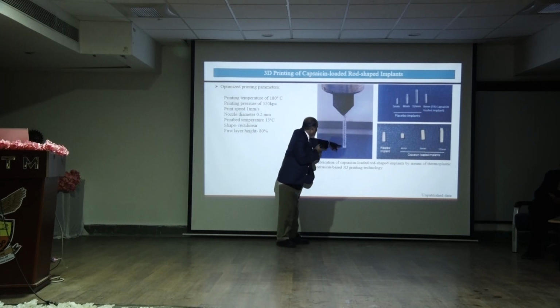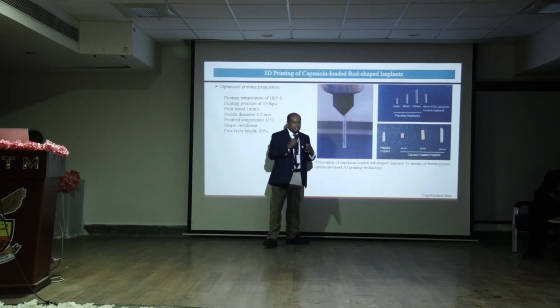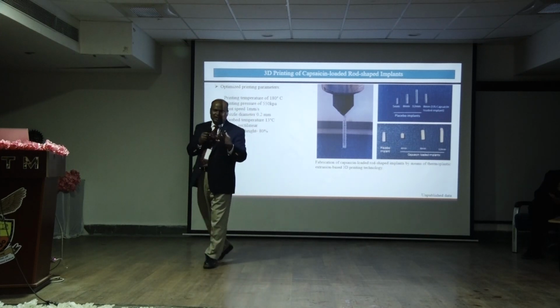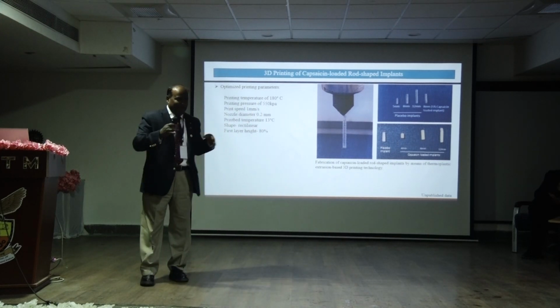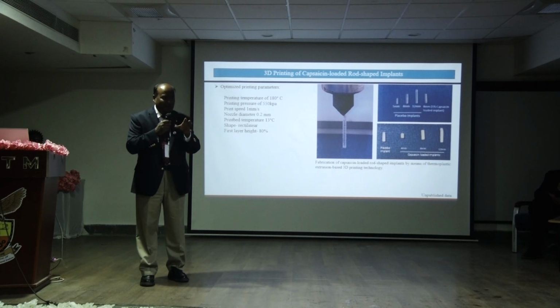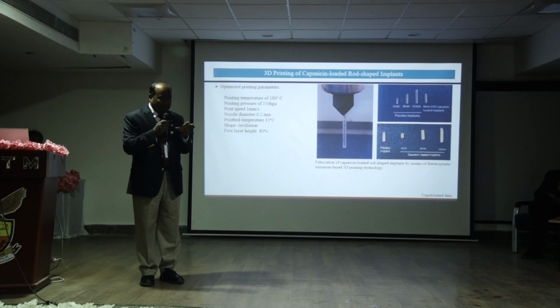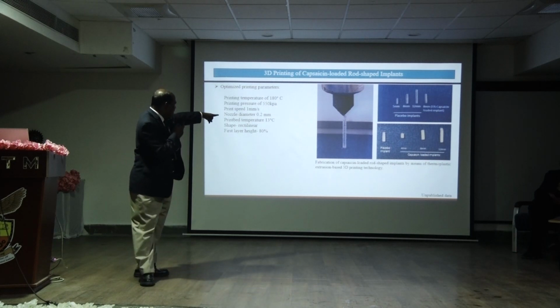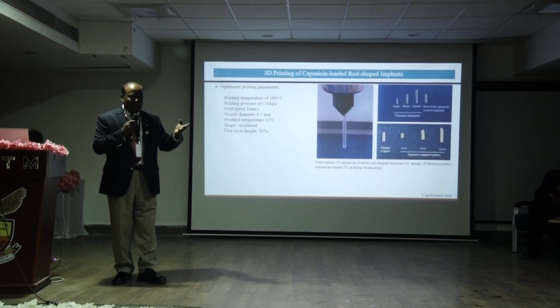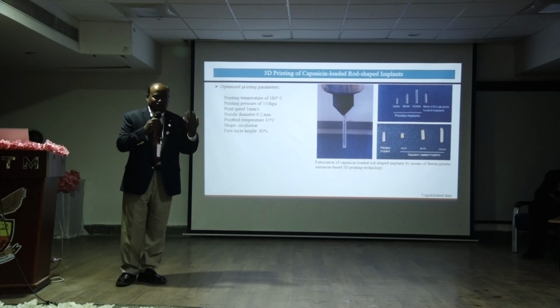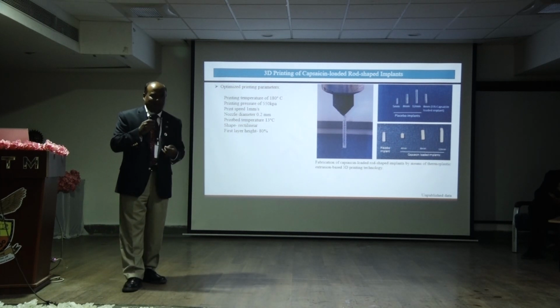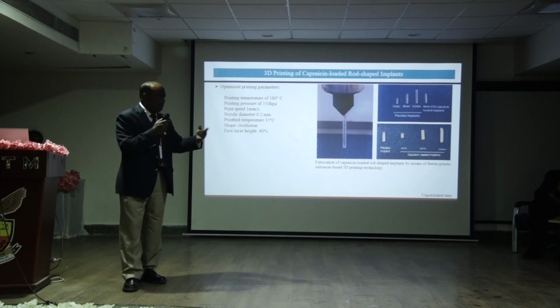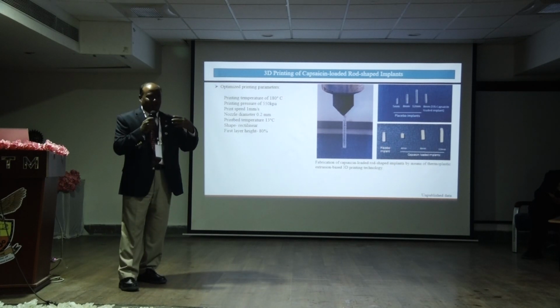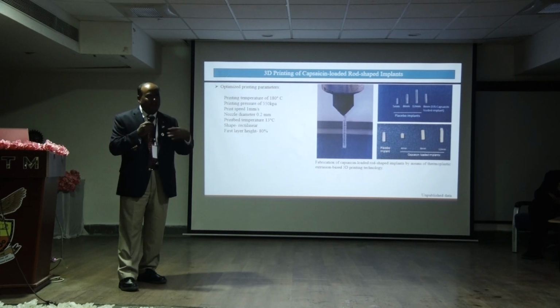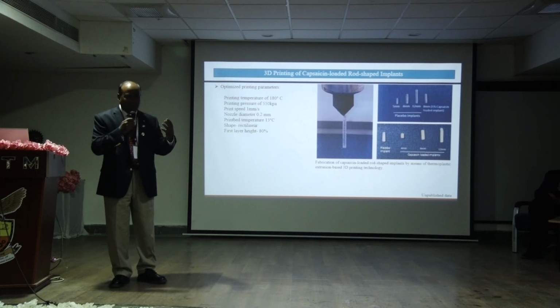The print head starts from here and builds the structure, and basically we melt the drug and polymer together, and inside we can control the temperature. We have a cooling, refrigerated environment inside the printer, so that it can build a structure like a tower. People might ask me, why can't we make conventional needles? Why do we need a 3D printer? 3D printing provides porosity for the implant, so that drug release can be modulated. So you don't need to play too much with the polymer. Basically, you can play with the structure so that you can modulate the drug release.